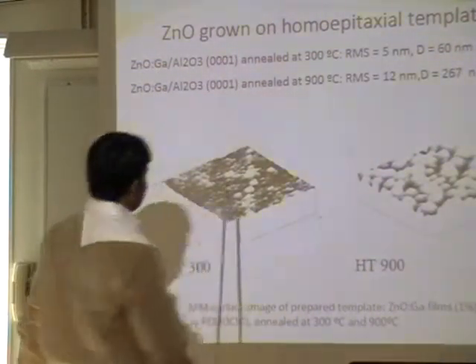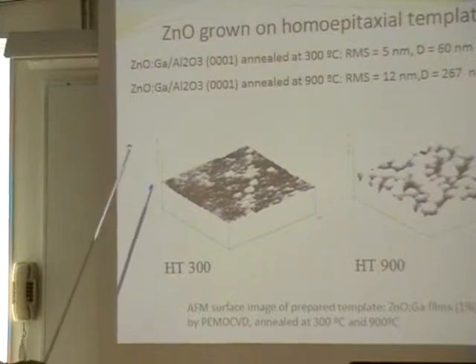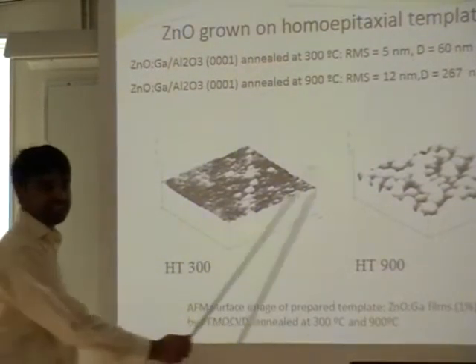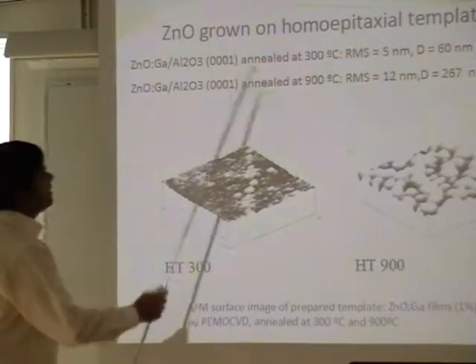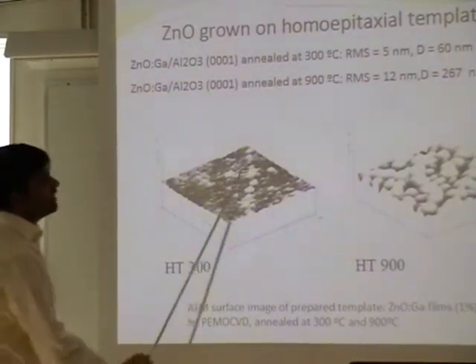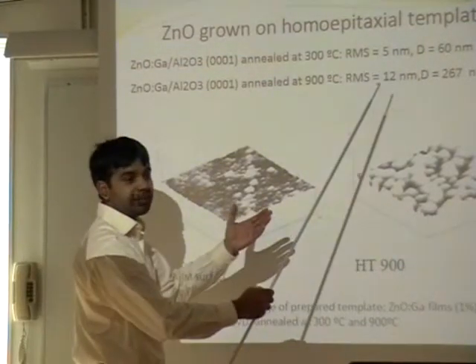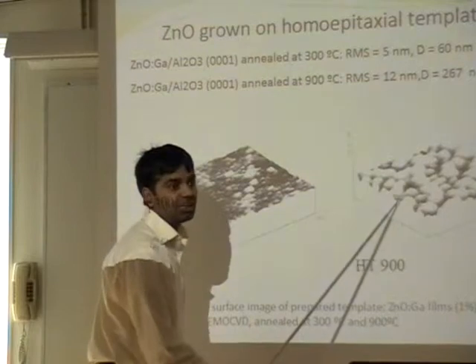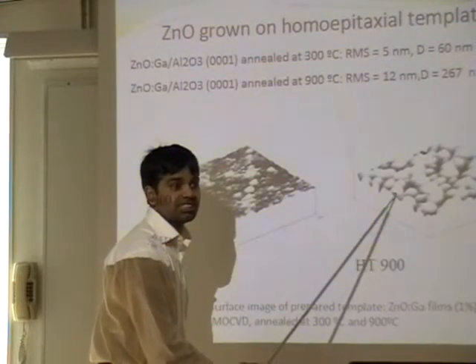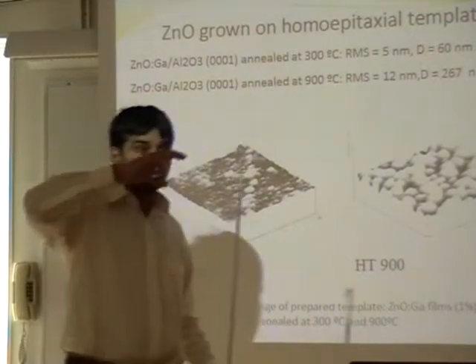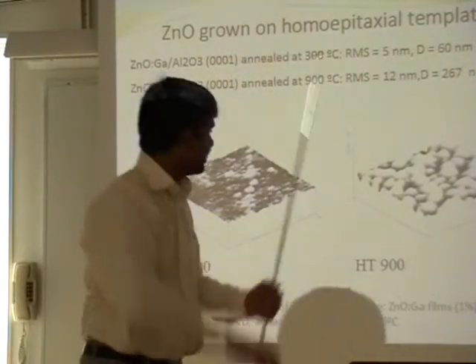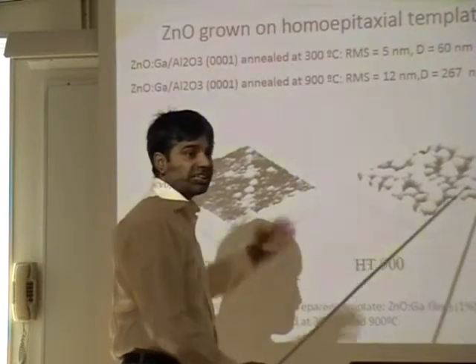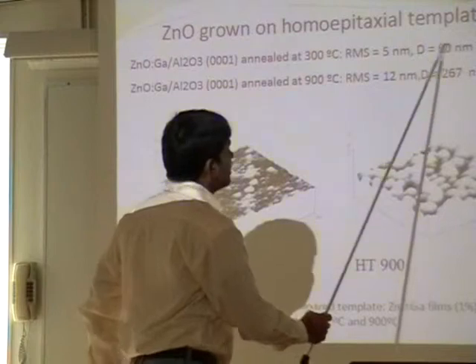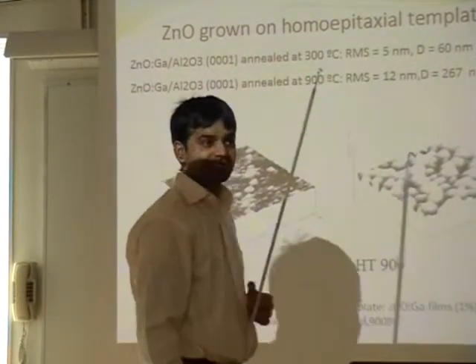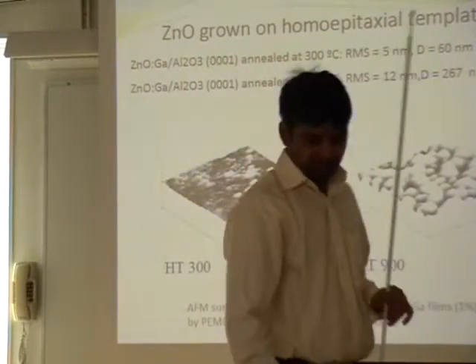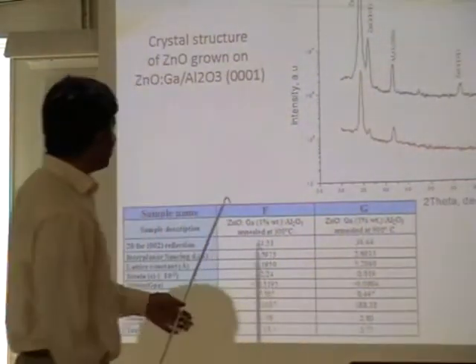Here, first through AFM. After annealing, we check the result. There is a small roughness. With increasing the annealing temperature, roughness also increases. The reason, due to the rapid growth of atoms, you can see, they create more roughness, and also grain diameter increased. And these are results.